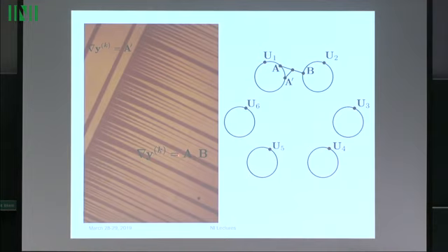So these are two variants A and B. They differ by a rank 1 matrix. So once again, what you do algebraically is you start at A, and A has two rank 1 connections. You choose one of them, and then you take something on the line between A and B. Lambda FA plus 1 minus lambda FB, that's that point, and you look for a rank 1 connection back to this well.